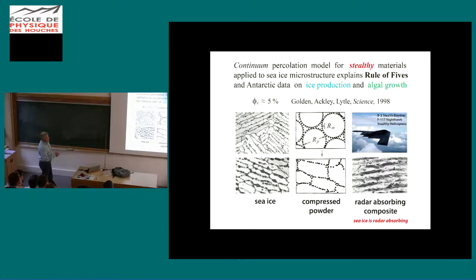The brine inclusions are not just randomly distributed. They live on the boundaries of these pure ice platelets. This reminded me of a microstructure I had seen previously, a so-called compressed powder microstructure, with big polymer spheres and little metal or carbon black particles. You want the whole thing to be conducting, but in particular, you want this material to be radar absorbing. But you can achieve conductivity and radar absorbing characteristics with very low volume fractions through this excluded volume effect.